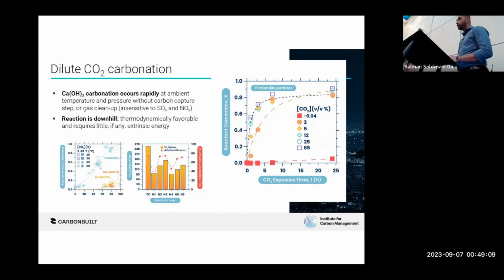In fact, there are two things to it. So calcium oxide does not carbonate really well. You form a passivation film of calcium carbonate on the surface, you arrest the reaction, it doesn't work. Calcium hydroxide is an interesting creature because, in fact, as you carbonate it, you've got a hydroxyl for carbonate exchange reaction, which produces water on the surface. The water continues to self-catalyze the reaction. So calcium hydroxide carbonates really fast, really effectively. What you're looking at here is carbonation, effectively extent of conversion as a function of time. You can get these reactions to run to near completion in 24 hours, even using 2% CO2.